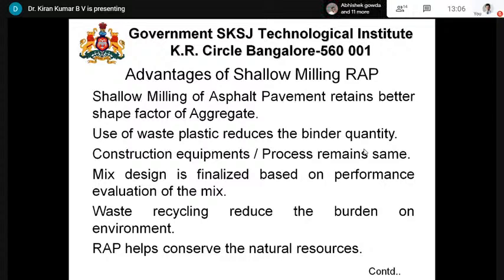The advantages of shallow milling RAP are much higher compared to normal milling, and the usage of plastic in this recycled asphalt is an additional advantage in two ways: it helps to eradicate the plastic problem, and it also enhances the performance of the pavement. It gives a higher moisture strength to this particular pavement, with less consumption of bitumen. Shallow milling of asphalt pavement retains a better shape factor of the aggregate. It will not damage it, because the milling diamond cutters in normal milling break the aggregate, and that is the reason in developed countries they use 40 to 50% of this material to achieve the density, with the missing fractions in the total recycled material